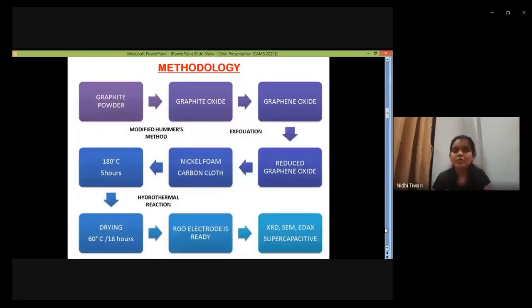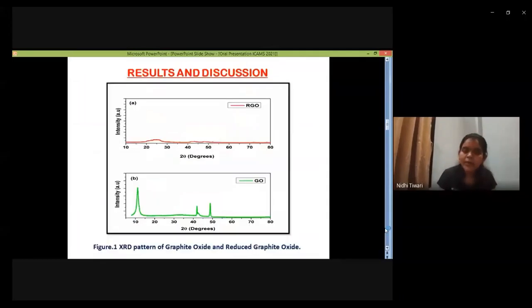The methodology follows these steps. First, graphite powder is converted to graphite oxide using the modified Hummers' method. Then graphite oxide is converted to graphene oxide through exfoliation in distilled water. Graphene oxide is then converted through a hydrothermal technique to reduced graphene oxide, and deposition is done on nickel foam as well as on carbon cloth at 180 degrees Celsius for 5 hours. After this, the electrode materials are dried at 60 degrees for 18 hours and then the ready electrode material is characterized using different characterization techniques.